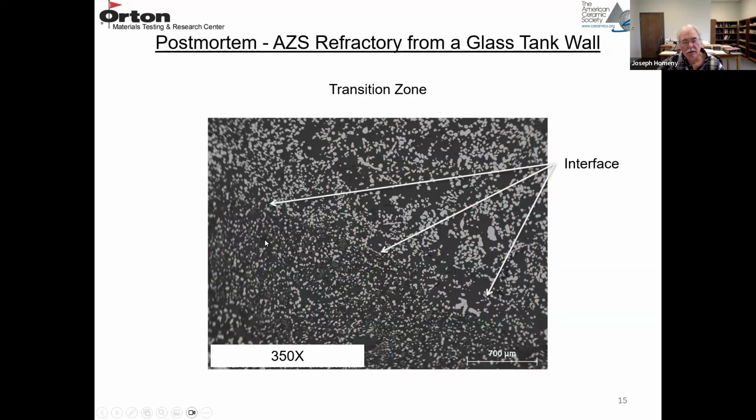So back in the interior, somewhere behind the hot phase, there's a transition zone. So there's a thermal gradient in these sidewalls. So at some point, there's a freeze plane, where the sodium and calcium diffusion stops. And that's right along this transition zone.